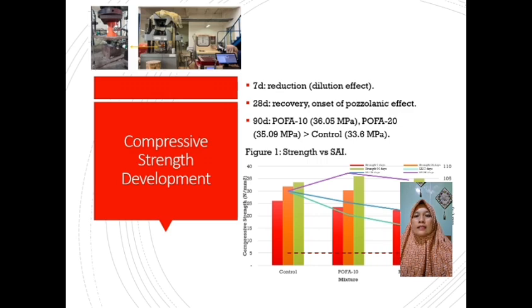POFA. The strength activity index indicates the performance of POFA compared to the control mix. On figure 1, we can see the strength activity index relative to the compressive strength. The results show that the strength activity index was around 90% at 7 days, and then 75% at 28 days, and above 100% at 90 days, for both 10% and 20% POFA.